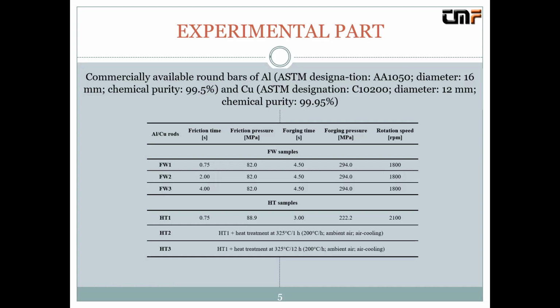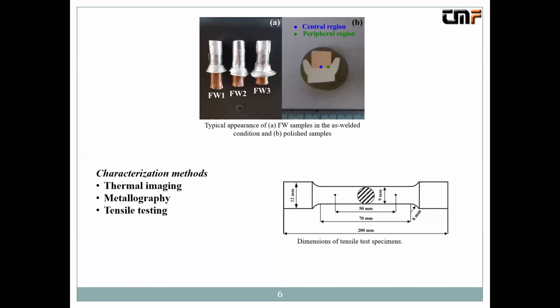But what's the importance? The first sample was without heat treatment at all. The second one was heat treated at 325 degrees for 1 hour, and then air cooled. And the third sample was heat treated at 325 degrees for 12 hours. So when we finished all the production procedures, we prepared some of the metallographic samples, and that's the look.